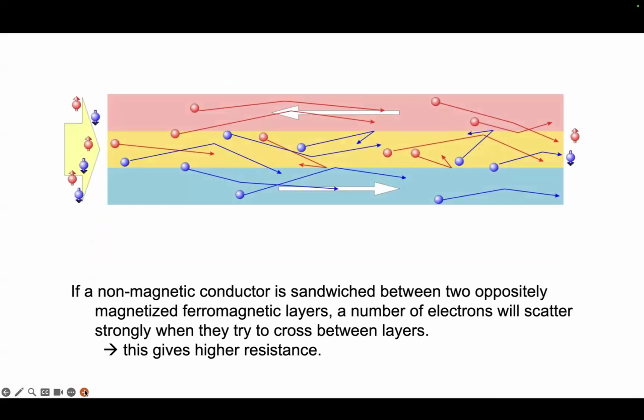However, if you take now a sandwich, which consists here of two magnetic layers and a copper layer in between, then you can see now that if we introduce current from the left-hand side into this sandwich, when the two magnetic layers have their moments in opposite directions, this means that electrons, let's say the red electrons, will be scattered in the blue layer and vice versa. So everywhere the electrons will suffer scattering if the copper layer is sufficiently thin compared to the mean free path of the electrons. The electrons, as you know, are moving in all directions.